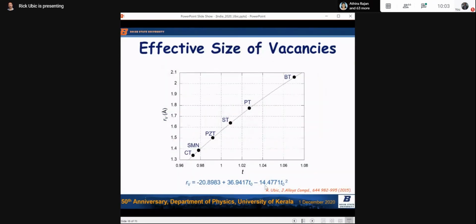All right, let's move along quickly. So you can graph the size of vacancies. This is our equation for vacancy size. And there's calcium titanate, with calcium vacancies about 1.3, so about the same size as calcium, actually. Strontium, magnesium niobate, PZT, strontium titanate, lead titanate, barium titanate, in almost all cases, apart from calcium. In fact, it's for some calcium cases, but not in all.